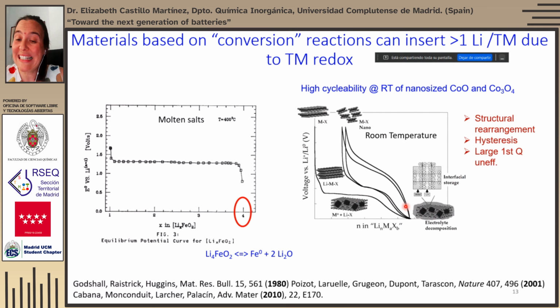Moreover, what is seen is that there is some additional capacity to that expected for the insertion of 1 or 2 or 3 lithium ions. And this has been assigned to some interfacial storage on the surface of the metallic nanoparticles, as well as to some possible further reactivity of the decomposition products of them. So although using these materials with huge gravimetric capacities would be very desirable, the large hysteresis and large first cycle Coulombic inefficiencies prevent them from going to market.